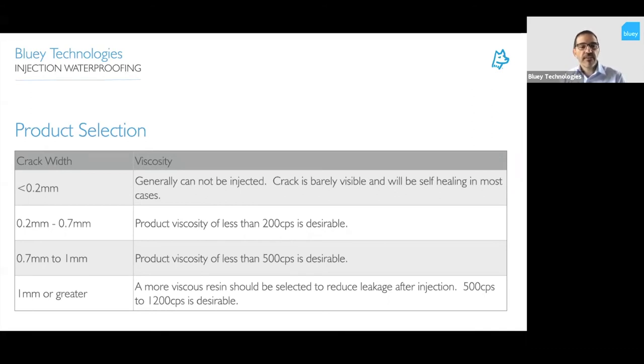0.2 to 0.7 is a pretty common range for cracks. They often occur in this range. It's a little bit just outside the minimum specification requirements. So we need a low viscosity resin, 200 centipoise is usually desirable or less, and reasonably high pressure as well. So you'd be looking at electric diaphragm pumps rather than a hand pump for that, for example.